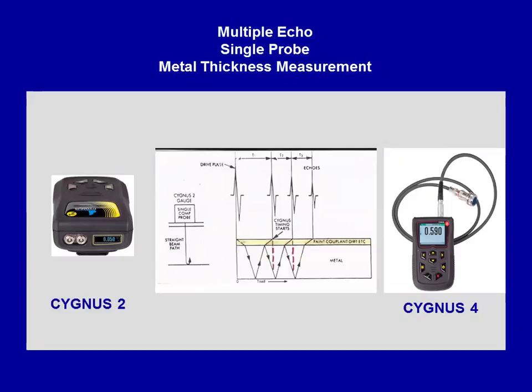As it passes through the paint, eventually it gets through it, going through it slower, but then it trips the clock. So now we start timing it. But at the same time, the sound's going back down in the steel. So by the time the clock turns on, it's actually down here, and we go through the same cycle a second time. As you can see, what we end up measuring is just one cycle of sound that's trapped between the two walls of the steel.